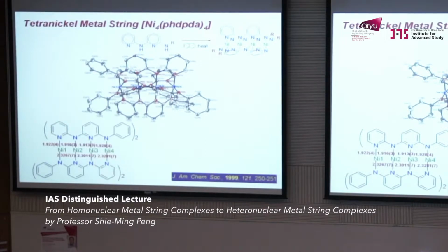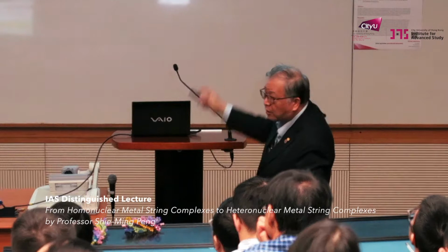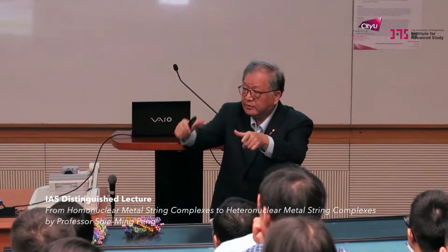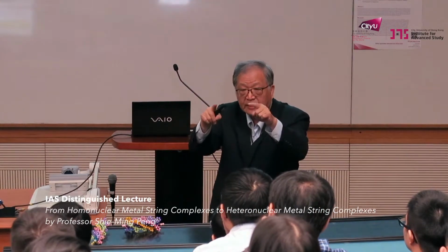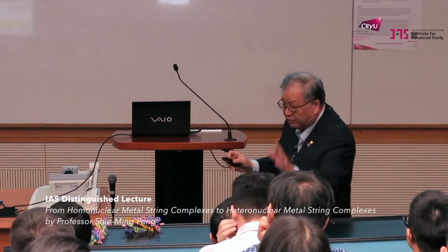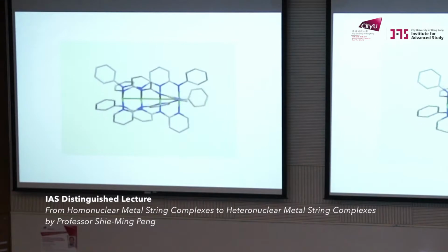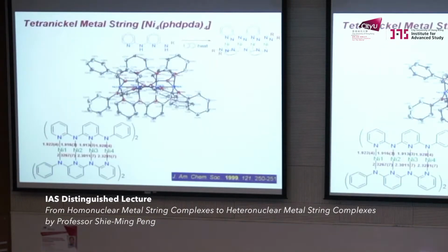Okay, from 3 to 4, we synthesize the dipyridyl diamido ligand. And we are certainly lucky enough, the student was lucky enough to isolate and get the crystal structure of the 2,2,6 isomer. Because as I mentioned, this is unsymmetrical. Quadrupole, you have many isomers. You have 4 heads in one direction, 3 heads in one direction and a tail, and 2 heads in one direction, and 2 heads in one direction have cis positions and trans positions. But they can get the crystal of this 2,2,6. And the structure shows that all the nickel has a short nickel-nitrogen distance. That means all the nickel are diamagnetic, and the whole complex is diamagnetic.